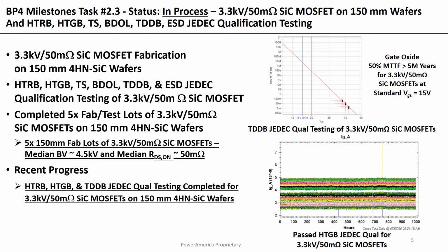Recently, we've had significant progress on JEDEC qualification of these 3.3 kV 50 milliohm silicon carbide MOSFETs fabricated on 150 millimeter wafers. This has included successful high temperature reverse bias JEDEC qualification, a successful high temperature gate bias JEDEC qualification, and also TDDB JEDEC qualification testing.